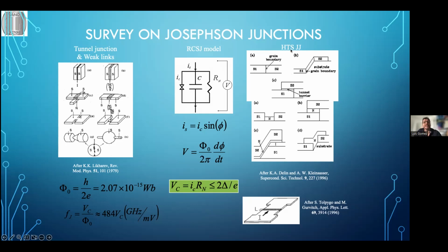So this is called HTS, high temperature superconductors. Basically you create something called a grain boundary. You use a substrate, and then you have a separation in how you grow the superconductor on one side, because these are crystals, and then the other. If you have a different grain orientation on these two high temperature superconductors, or it could even be the same, but there is a clear separation between the superconductor on the left side and the one on the right. So that would be one type. You can see some effect in this type of material.